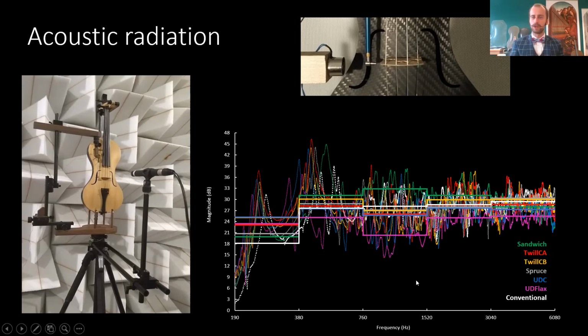And so when we want to examine the sound of a composite material, we immediately see that it depends very much on which material you use. So flax fibers or carbon fibers, a core or no core, it makes a huge, huge difference. So there is no such thing as the sound of a carbon fiber violin. It depends very much on how you make the carbon fiber violin or the flax fiber violin, etc.